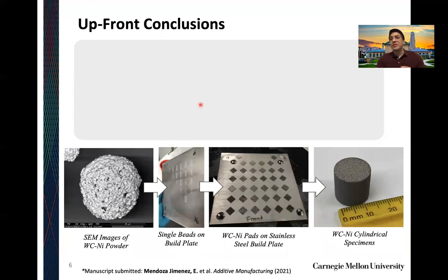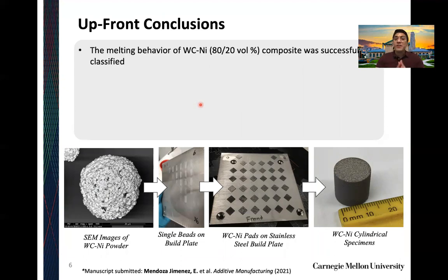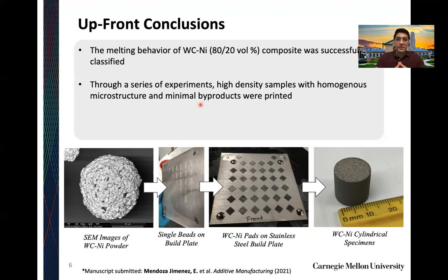So I'm actually going to spoil the talk a bit. I like to start off by giving my upfront conclusions just to motivate the work even further and so everyone has an idea of what's going on. The first conclusion is the fact that the melting behavior of tungsten carbide nickel, in our case, we used an 80-20 volume split, was successfully classified. So we actually did manage to fully melt this material system, and from there, we were able to build up parts. Through a series of experiments that I just discussed, we printed high density samples with homogeneous microstructure and minimal byproducts, which is really great if you're looking to build up parts for specific applications.